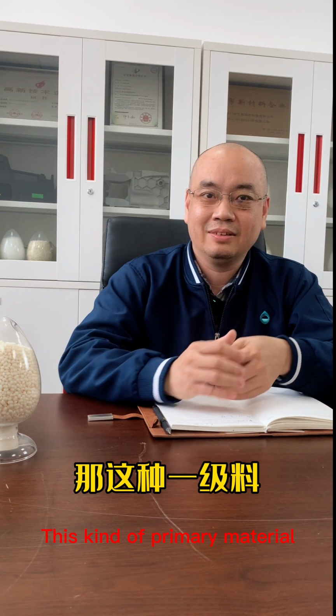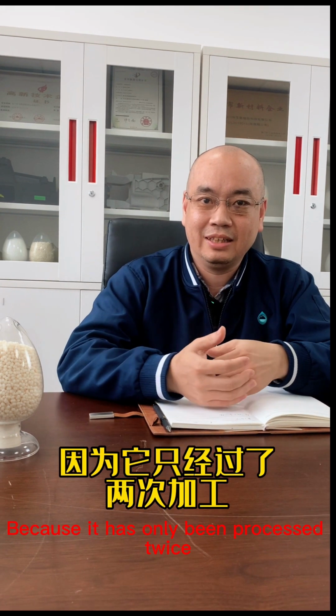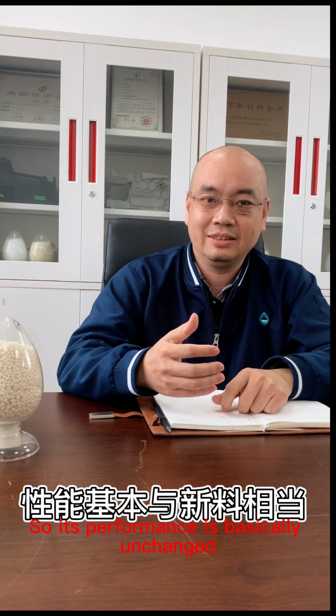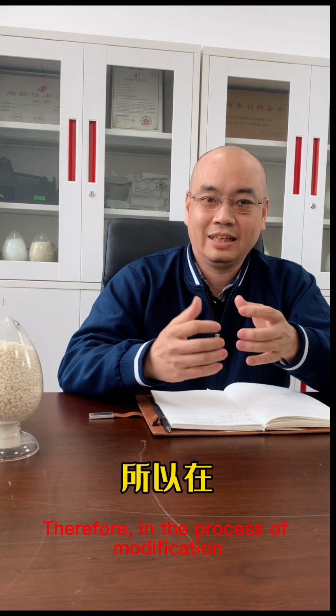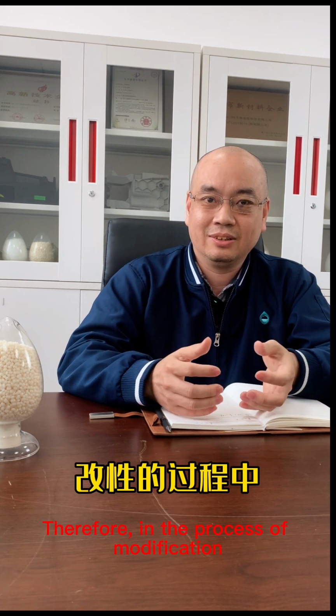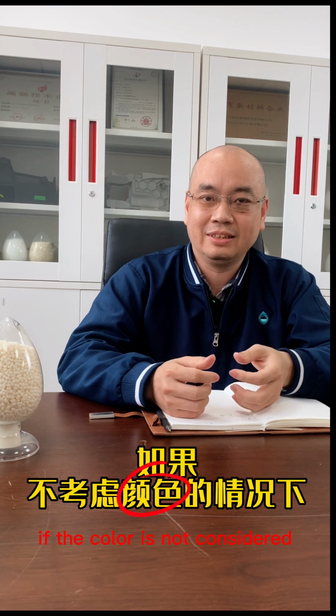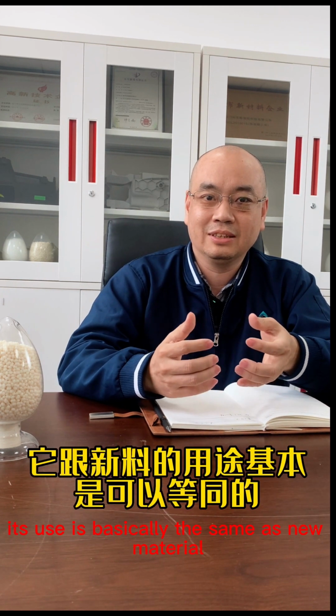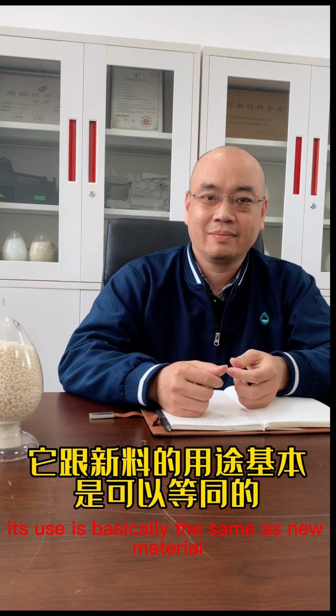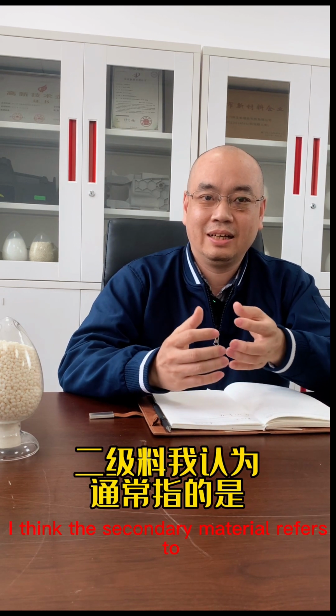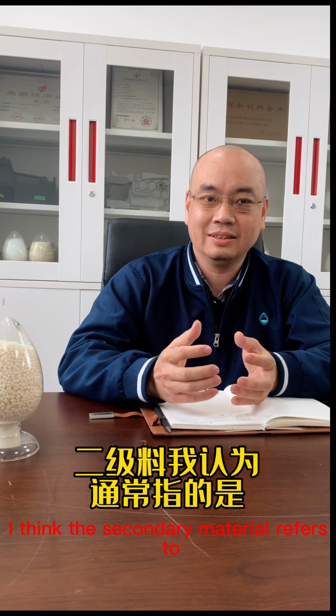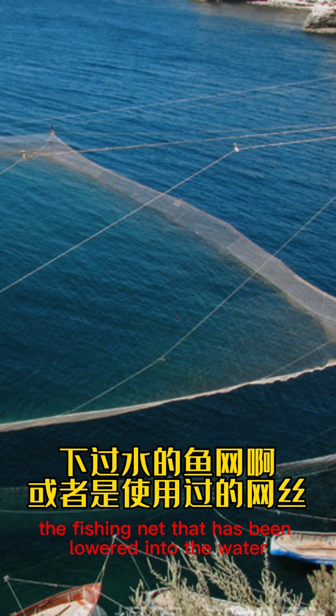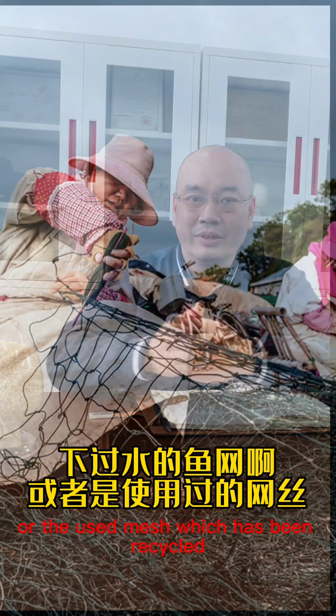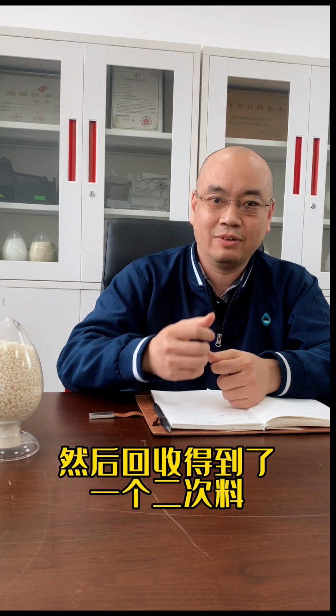This kind of primary material has only been processed twice, so its performance is basically unchanged. Therefore, in the process of modification, if the color is not considered, its use is basically the same as new material. As for secondary material, I think the secondary material refers to the fishing net that has been lowered into the water, or the used mesh which has been recycled.